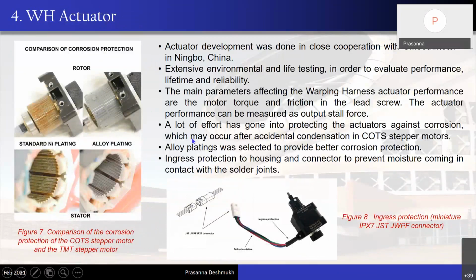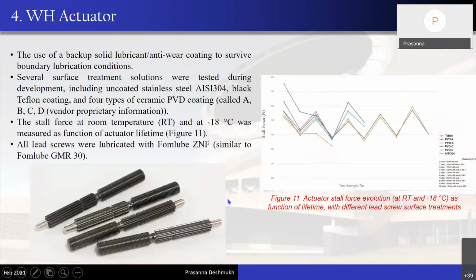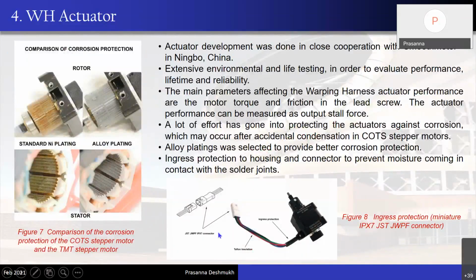So as an example, during the first initial test using commercially available components, as you can see, this particular rotor and stator gets corroded because it has only nickel coating. This was updated further with a nickel-based alloy, and we were able to get very good corrosion resistance on the new actuators after the test. As you can see here, we have used a different type of JST connectors which are IP protected, so we were not expecting any water to leak inside, which we were observing in the previous cases. So that particular correction was also done.